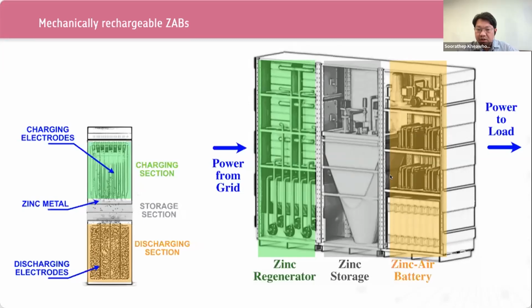Such a system can function over a wide range of concentration and current density, and preferably operates in a certain range of concentration. During charging, as zinc deposits form on the cathode surface, they can be regularly removed and transported by gravity downward into anode beds. Once the anode assembly is completely filled, zinc deposits tend to accumulate and gather in the region above the discharging cathode and beneath the charging electrodes.